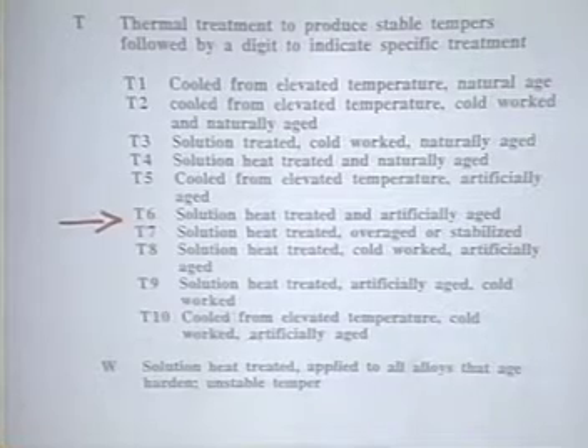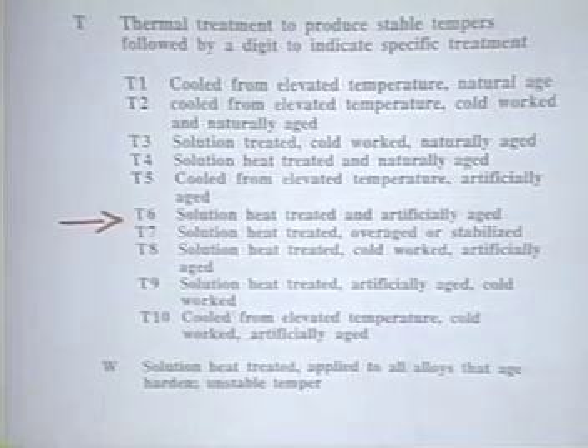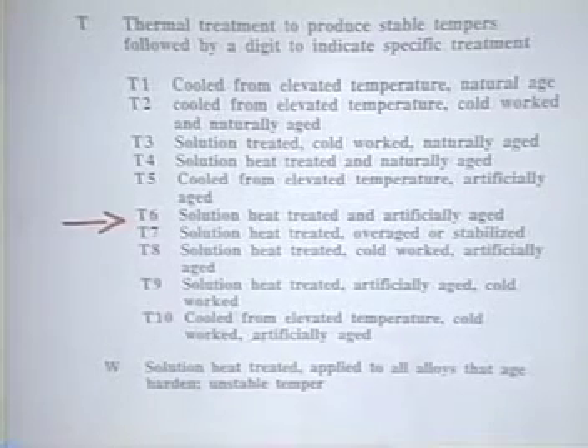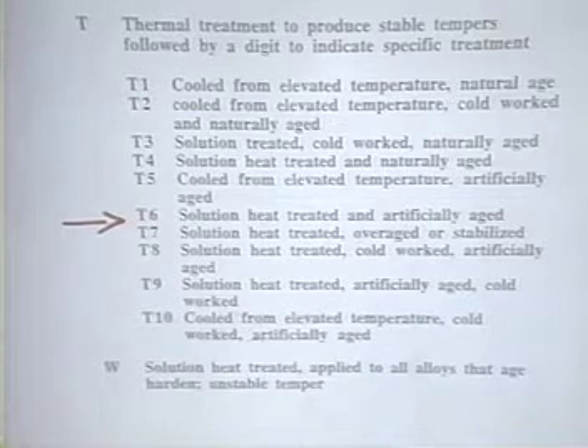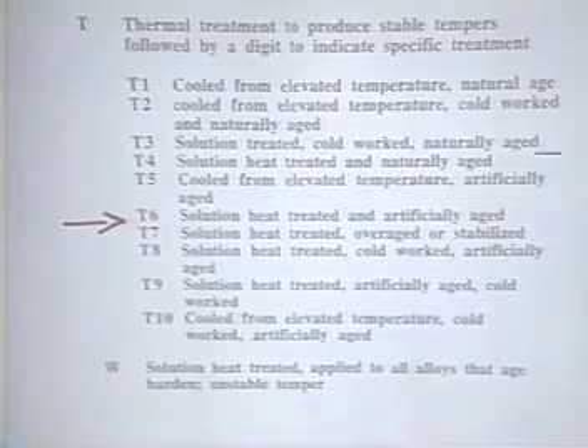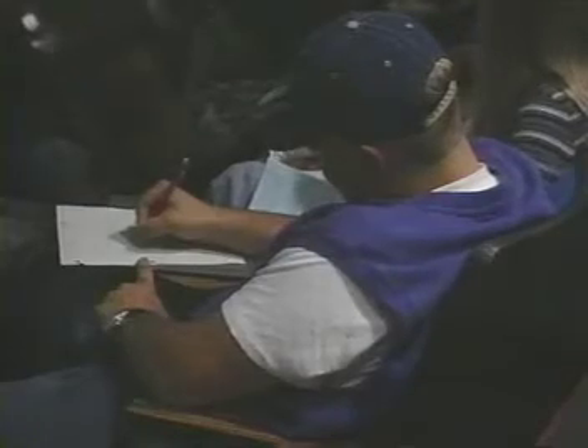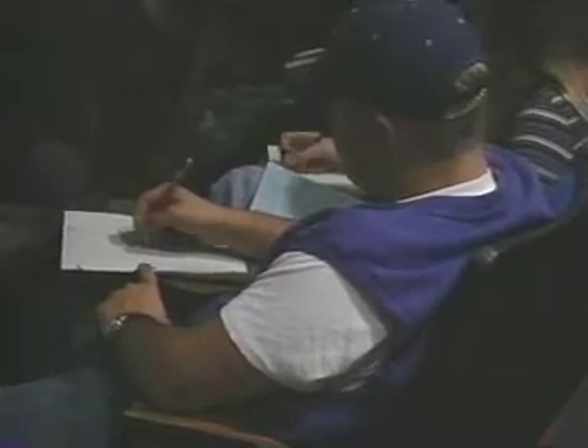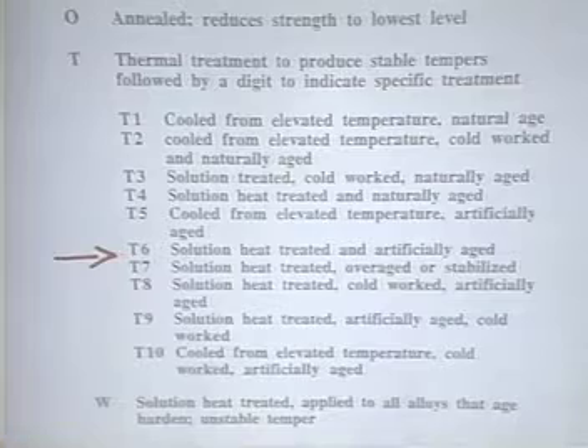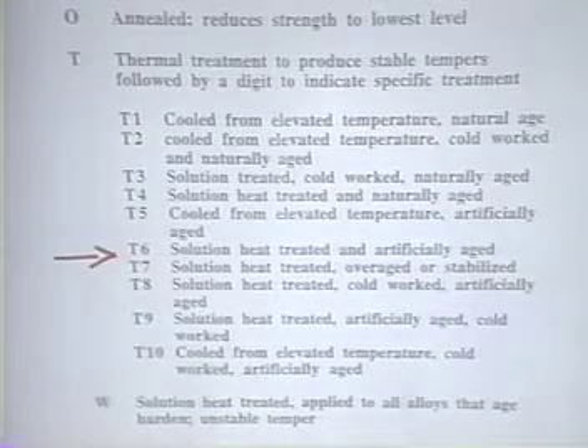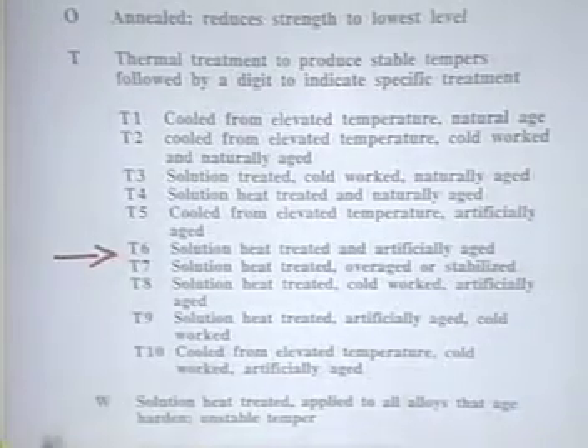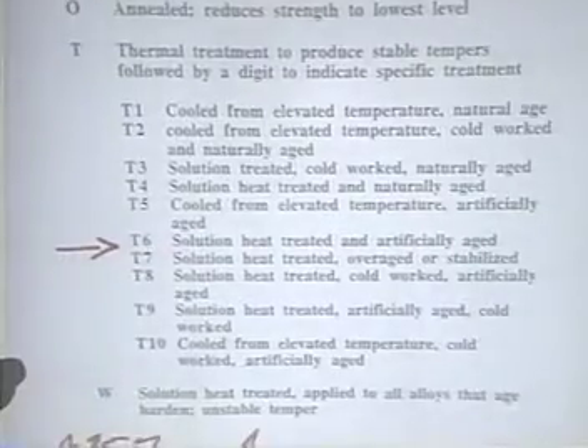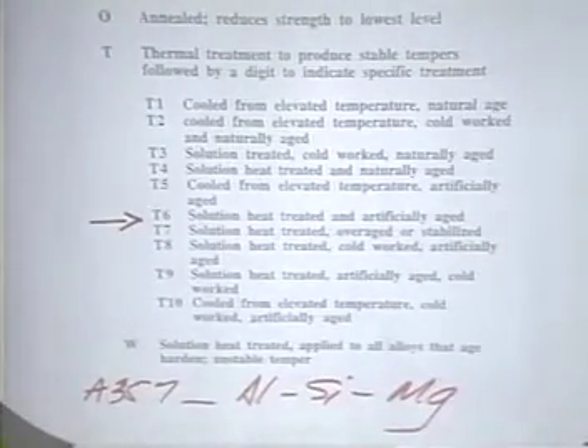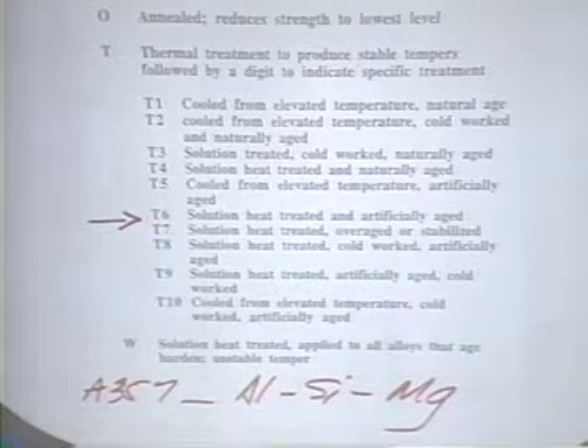Now, we can use this to an advantage. If we look at the T6 temper, particularly for a cast alloy like A357, which is used for a lot of structural applications, a lot of aircraft applications. There was a Navy plane that we were working on that had a cast 30-foot bulkhead of A357 in the T6 temper. So all we did was, by treating it, by tempering it, which is just a heating and cooling cycle, we changed the properties. We know that in the normal condition, we can't dissolve much silicon, for instance, and much magnesium. A357 is an aluminum silicon magnesium alloy, 7% silicon. The solubility is 1.2%, so the rest of it's left there.